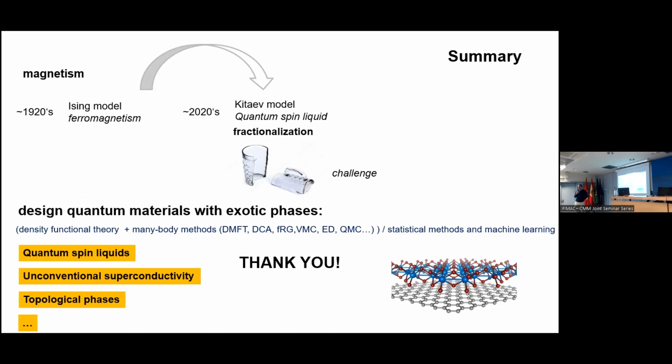Yes. So will you finally say that the quantum spin liquid has been observed? Well, I think the problem that one is fighting with these quantum spin liquids is always disorder. And in all these systems, and that's why the experimentalists are trying to get better and better samples, disorder kills the state very easily. So I wouldn't say that we have a clear case of quantum spin liquid, but I can say that one sees an evolution where we are seeing more and more signatures of this state. It's very different from the quantum Hall effect, where disorder doesn't matter for the state because Landau levels are Landau levels, but here, forget it, it's very sensitive.